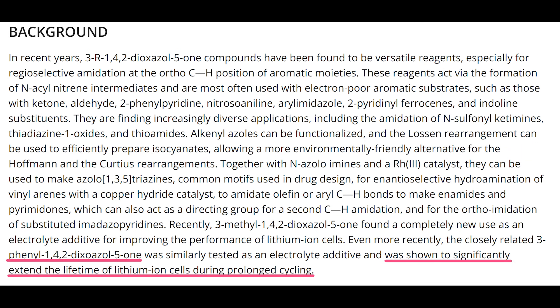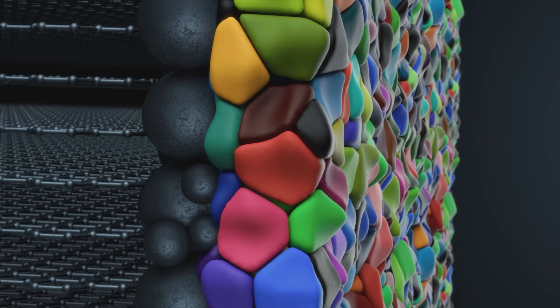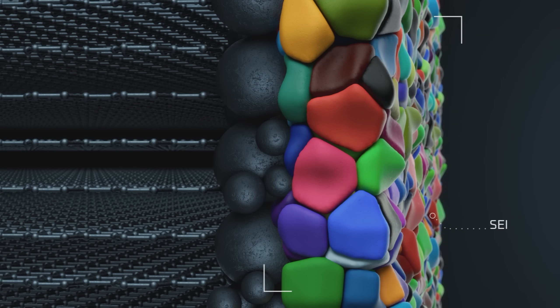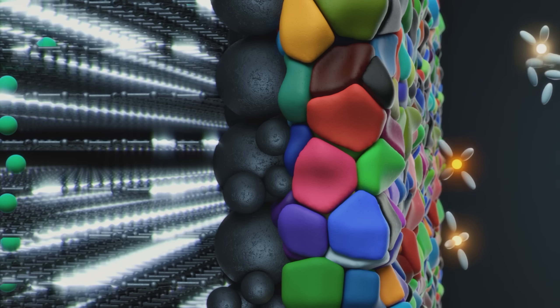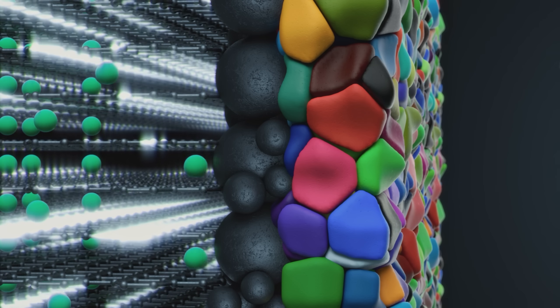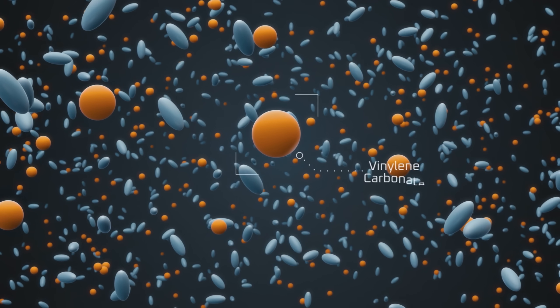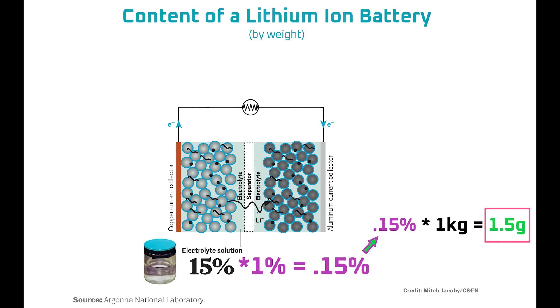The useful information I did find was in the background information part of the patent. First, PDO is being tested as an electrolyte additive to extend the lifetime of lithium ion batteries. The way electrolyte additives work is by reacting with other chemicals in the electrolyte solution, like lithium, to form a protective layer on the anode of the battery, but also to a lesser extent the cathode. That protective layer prevents the electrolyte from continuing to react with the electrolyte solution, which would cause the battery to degrade and quickly lose cycle life. That means even a small amount of additive can dramatically increase cycle life. For example, adding 1% PDO to a battery can triple its cycle life, which is less than 2 grams for a battery cell that weighs 1 kilogram.